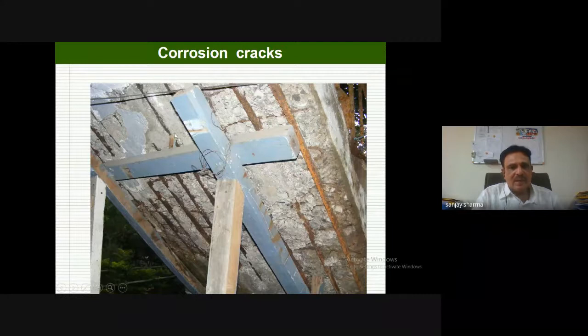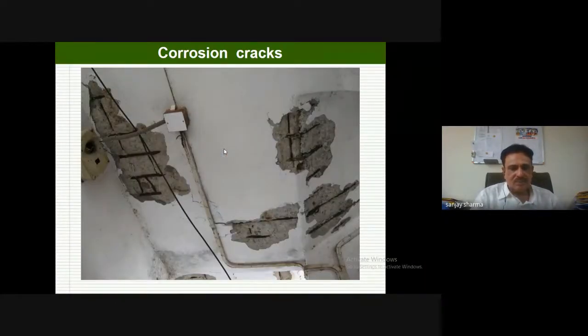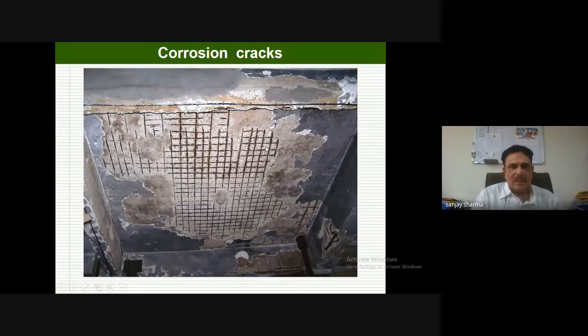But in the case of corrosion due to chlorides, the chlorides are already there inside your concrete, and the same phenomenon occurs, because it lowers the pH value. When it reaches the bar, there will not be any sort of crack appearing on the surface, and the failure will be sudden. When the debonding takes place between the cover concrete and the reinforcing bar, the cover concrete will fall out immediately. There will be small corrosion spots on the surface, but otherwise you will not see anything wrong. So basically, corrosion due to chloride is sudden. As you can see, this is the corrosion due to chloride.